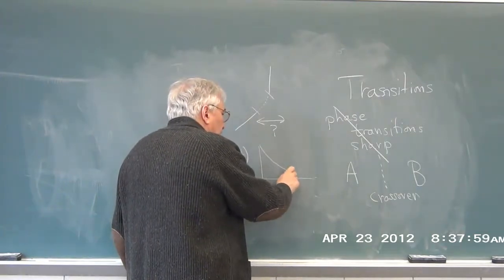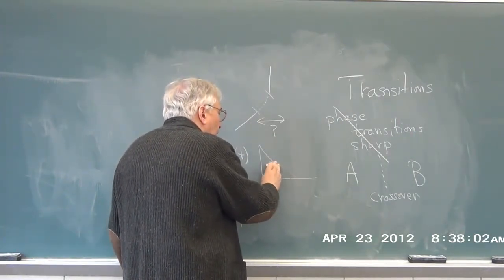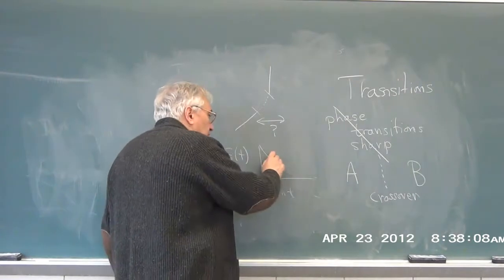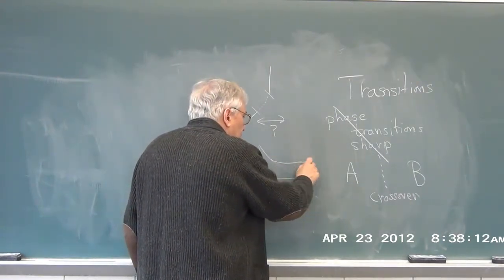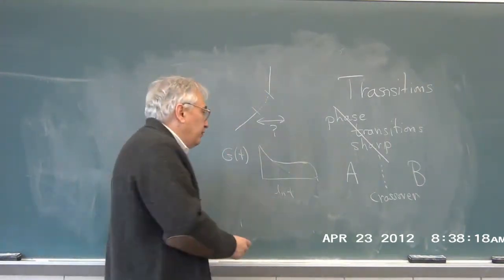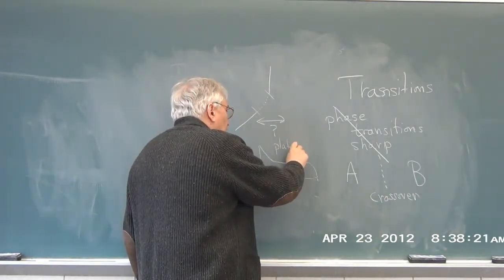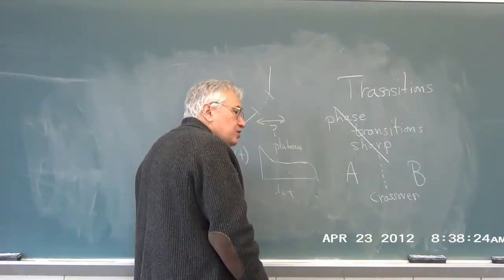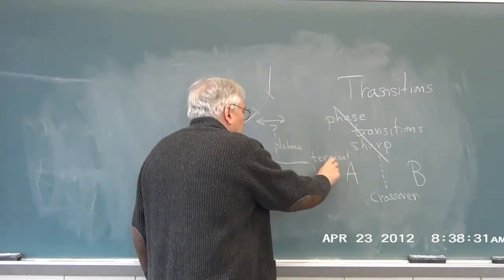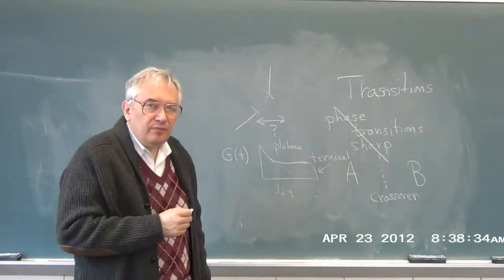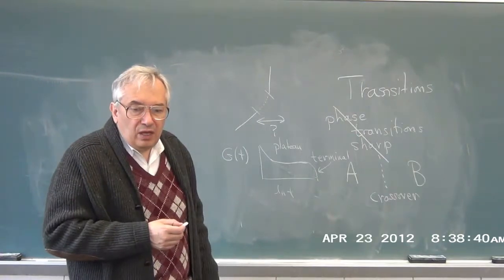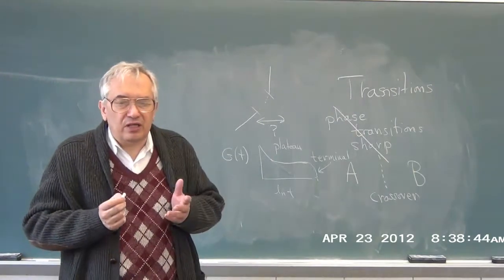And it looks sort of like this, except if you go out to, and we better make this log time, if you start making the polymer solution concentrated, you eventually end up with a relaxation which is extremely long-lived and which has a plateau. It's not really exactly a plateau, it just doesn't change very much. And then down here, long times corresponding to short frequencies, you have what is called the terminal regime. And so that is, in a sense, a transition. You start seeing this plateau.